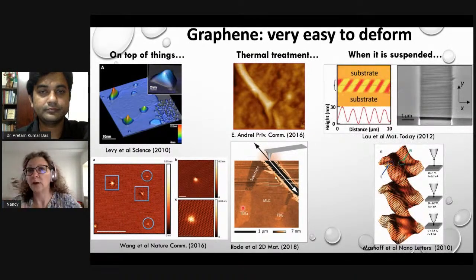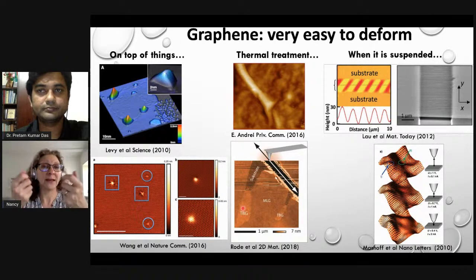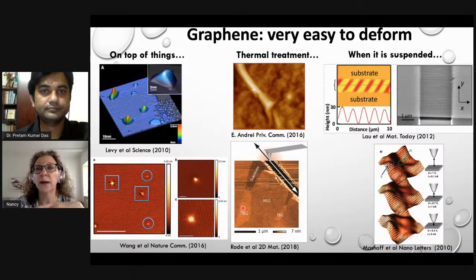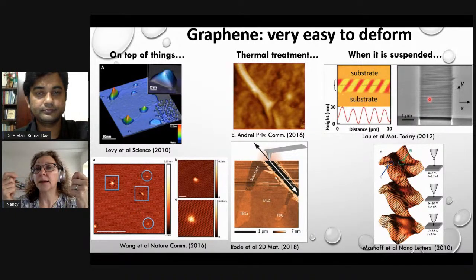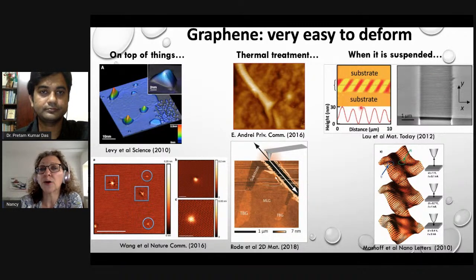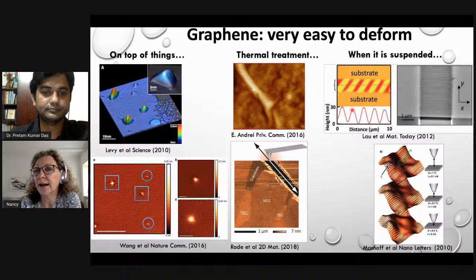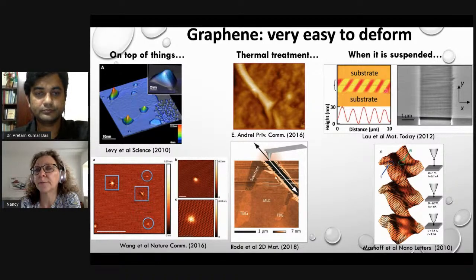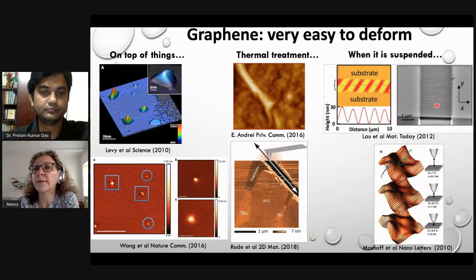And the most trivial way of seeing deformations is when you have the material suspended. In all these cases, the material was on a substrate, but when you have the material suspended and you stretch it, you see that there are these modulations. This is bilayer graphene, this is monolayer, and you have modulations. These are measurements of the different heights that the membrane has in different positions, and you see that you have periodic modulations. The material goes up and down, up and down. These are ripples that form under strain, and that in bilayer graphene are visible in plain sight.